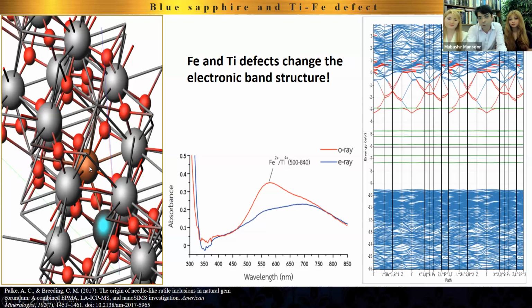But since we included now titanium and iron, this structure changed. And now we have these lines in between, which are the allowed states. It's like the electron now has these very, very nearby ladders onto which it can climb. And it can climb with very low energy, with energies of about 2 to 3 electron volts, which is equivalent to the sunlight. And that is the reason why we can actually create the blue color from the iron and titanium that come together in the sapphire structure.